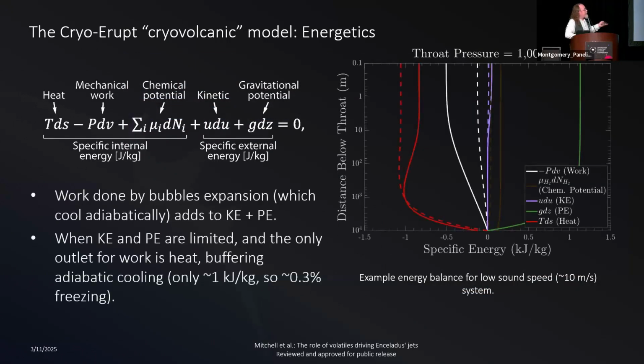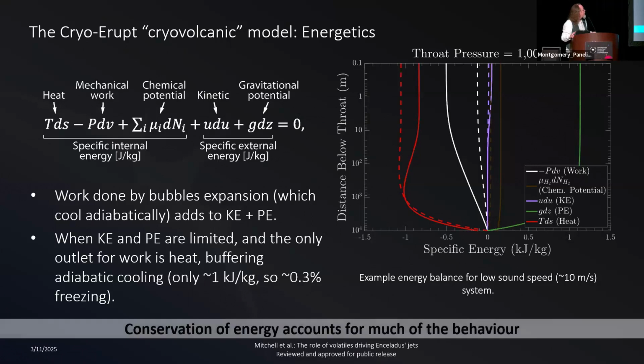We solve for conservation of momentum, energy, and mass. Here is our energy equation. Basically, again, the work done by the bubbles adds the potential energy and kinetic energy. Once you've hit a speed limit for kinetic energy, which happens if you've got a supersonic nozzle in the system, then all the rest of the work goes into heat, which stops you from freezing because of all the adiabatic expansion of the bubbles. We actually end up with only 0.3% in this case.